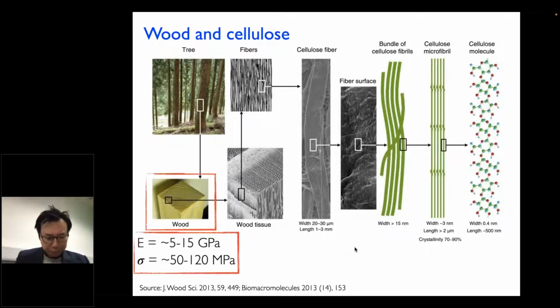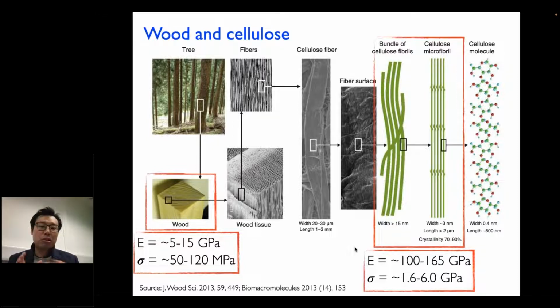Now, why do we care about cellulose in this context, right? So if we consider wood as an example, typical wood has modulus of 5 to 15 gigapascal, strength 120 megapascal. As a standalone material, it is a good enough construction material. If you pulp it down to the extreme right, effectively a cellulose molecule, in those cases, you're trying to break that carbon-carbon bond, probably about 20 gigapascal to actually break that carbon-carbon bond. But what we're interested in is that particular length scale, that sort of cellulose microfibril, elementary fibrils, bundles of fibrils type length scale with sort of dimensions of approximately 50, 60 down to sort of 4 nanometer in width. At those length scales, your modulus is up to 165 gigapascal. That is twice as much as glass fibers. At that length scale, those nanofibers, they are 6 gigapascal. So that's actually twice as strong as glass fiber. So that actually provides us with an interesting alternative to actually replace glass fibers with these sort of cellulose nanomaterials.